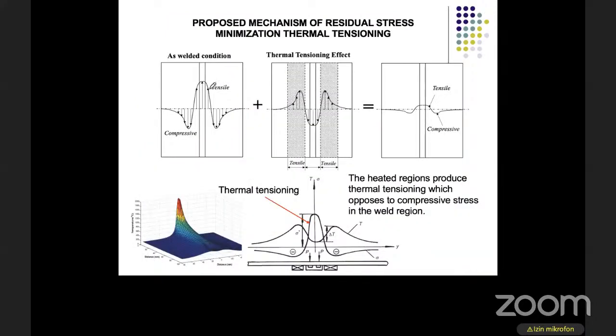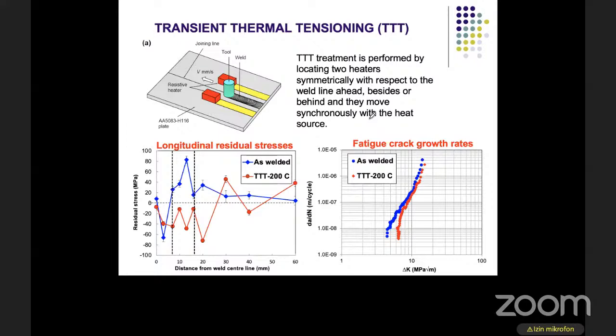And then this is the mechanism of how STT can minimize welding residual stress. Actually, the introduction of local heating here produces what we call thermal tensioning, and thermal tensioning is opposed to the shrinkage stress caused by the weld. So the resultant of the stress load will minimize each other. And then next, we developed transient thermal tensioning (TTT) treatment, and we located two heaters symmetrically, and they just move together with the heat source tool or torch, and again we measure residual stress.